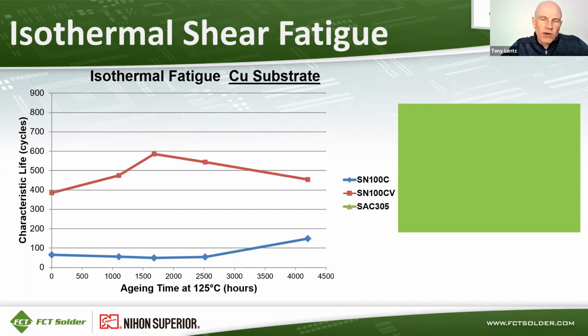So here's isothermal fatigue data on a copper substrate. Characteristic life is on the y-axis and aging time on the x-axis. That's the curve for SN100C alloy, which is fairly stable over the life of this test. There's SN100CV, which has a higher characteristic life than SN100C. And it is also stable over the life of this test out to 4200 hours.